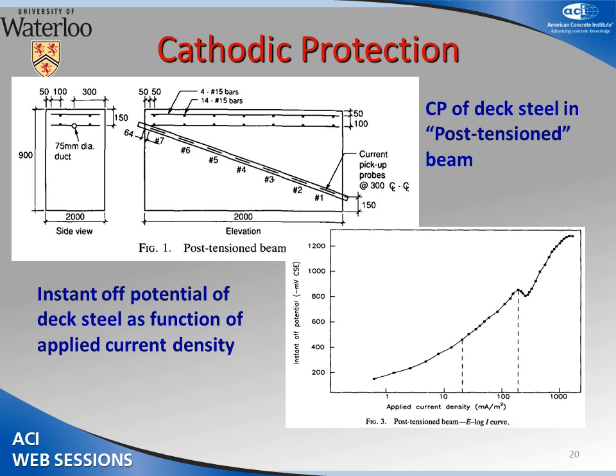Another aspect of his work was in cathodic protection. This was one of the experiments he did early on, where he looked at the cathodic protection of a, quotes, unquotes, post-tension beam. This is the beam. He had what he called deck rebar up here, and the post-tension cable duct was here, but instead of having post-tension cable, he had small coupons from which he could measure corrosion. And he was applying a current from a conductive paint from the surface and measuring the proportion of the current that went to the deck rebar, to the duct, and to these embedded probes.